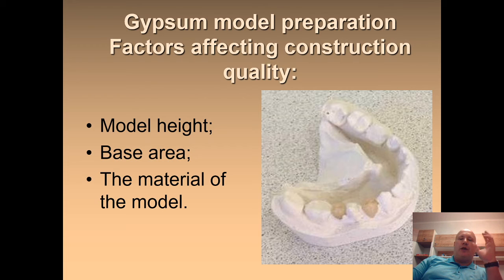Gypsum model preparation is one of the most important parts to get a good accessory using vacuum molding. Factors that contribute to the manufacture of a good model are vertical height, base area, and material of the model. First, the vertical height of the model. The results provided by the vacuum molded adaptation are associated with the vertical height of the model. As the vertical height increases from the edges of the cutter of the base of the model, the amount of pressure or suction suitable for molding accessories is reduced. This results in poorly fitted accessories.